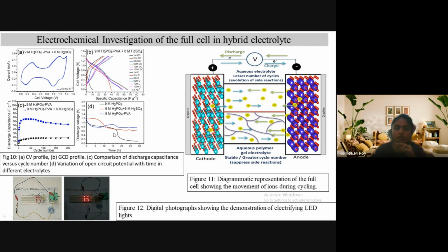So here we could see the self discharge of these three combinations, and we could see that for the aqueous electrolyte, after 30 hours it self-discharged up to 0.2 volt. But for the PVA based gel electrolyte and the hybrid electrolyte, it was up to 0.8 volt. So it reduces the self-discharging rate. So what is happening in the discharge mode?